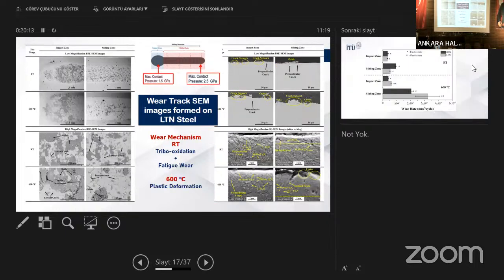In the case of low temperature nitriding at room temperature, fatigue wear and oxidation wear are operating. The surface was compound layer free, a metallic surface, and at high temperature under sliding contact, plastic deformation has taken place. Those protrusions are evidence of plastic deformation. So low temperature nitriding does not have any benefit whenever we use it at high temperature. It can only be used at room temperature.